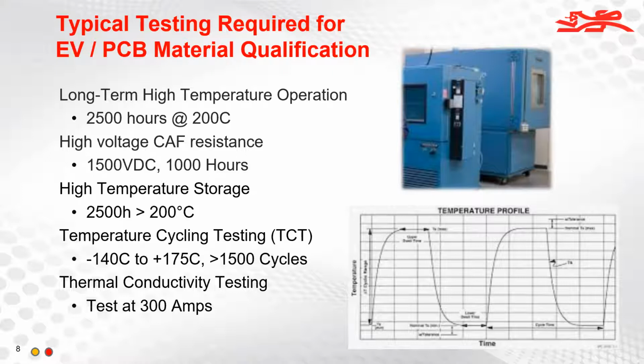So anyone who's familiar with some of the testing that has been typically used with printed circuit board materials in the past with traditional epoxy materials, some of these numbers here, they're just off the charts. In typical applications, for example, you'd be talking about a CAF test, you might be talking about 100 volts. We're talking about 1,500 volts. So these numbers are really off the charts, but this is the kind of demanding, harsh environment that is required for high voltage. I can tell you most FR4s, epoxy-based FR4s, at 2,500 hours at 200 C would be pretty dark in color after that amount of time at that temperature.